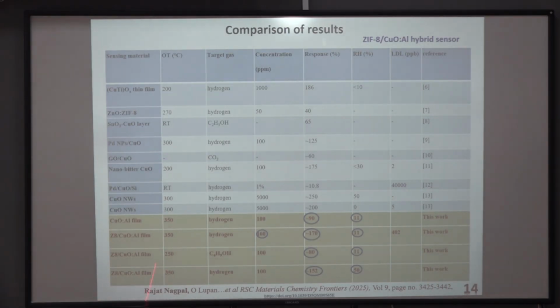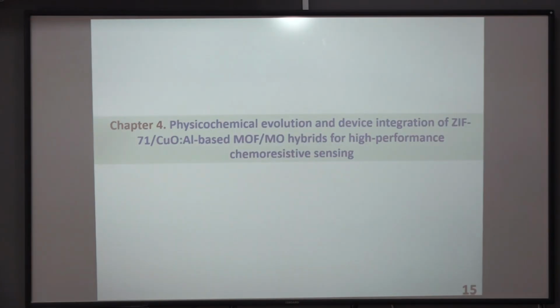And comparing it with other reported literature, here you can see the developed hybrids show appreciable sensing response comparable to other reported literature, but at very low concentration compared to other reported literature, which gives an edge to this work. Even at high relative humidity of 50%, we can see appreciable sensing response.